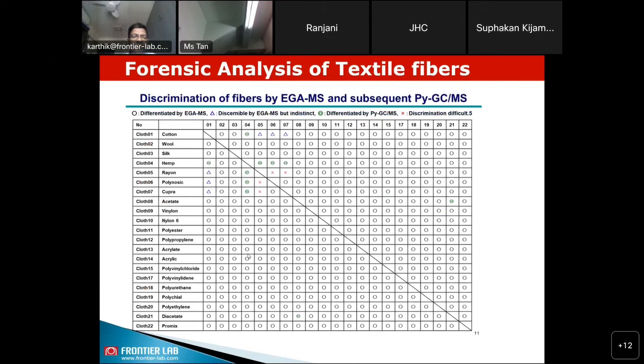So using this data, we were able to differentiate 21 different fibers. Based on the sign, the circled ones are differentiated by this evolved gas MS data, but for some, we can differentiate but the differentiation is not very distinct. That means you have to bring in another type of analysis called pyrolysis GCMS, where you employ GC for complete separation of the different pyrolyzates. That will provide more information that will add value to this differentiation. Out of the 21 fibers analyzed, there were only a few fibers that we were not able to differentiate, but most of the others we were able to differentiate with either the EGA-MS data or the Py-GCMS data.